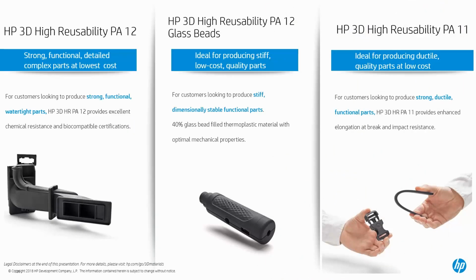Currently the materials that we have available are nylon 12 glass beads, and nylon 11. Depending on the product you're trying to create, they all have different benefits. If you're looking for a stiffer part, you would move more toward glass beads. If you need a more flexible part, you would move more toward nylon 11. And your all-around material that most people use is nylon 12.